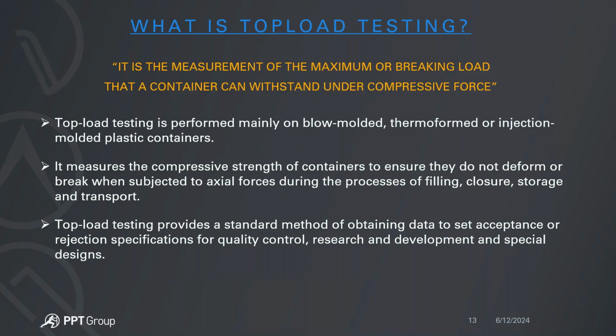So how do we know that we'll be able to stack plastic water bottles in their cartons 10 high, 5 high, 20 high, without the ones on the bottom actually buckling, right? We can only make that determination when we have the actual top load values to say, all right, these 20-ounce bottles can withstand 200 pounds of axial force. So if we stack them 10 high, they should be fine. However, if we stack them 20 high, then the ones on the bottom might actually buckle or fail. So these are some of the reasons why.